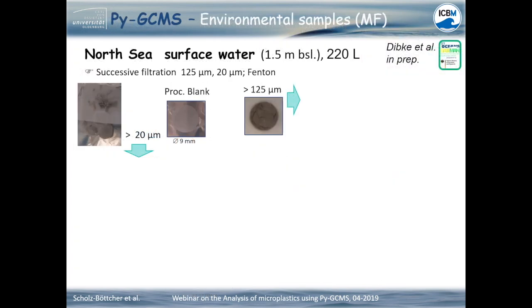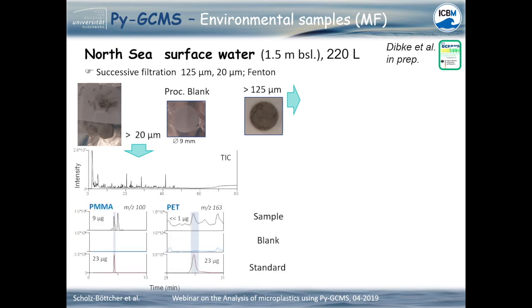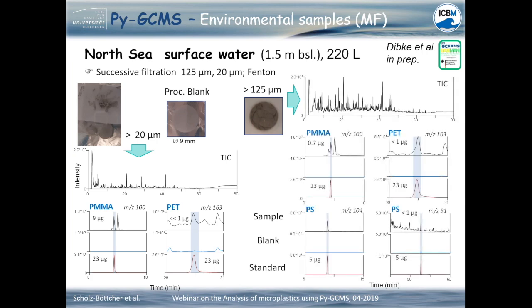The third example shows the results of a successive filtration of 220-liter North Sea water. The microplastic content shown for this volume is very small and in the range of quantification limits. However, 3 different microplastic types are detected, and the 2 fractions, bigger than 20 micrometers and bigger than 125 micrometers, show differences, which have to be discussed. The overall observed concentration of the sample series analyzed range between ppt and ppb levels.